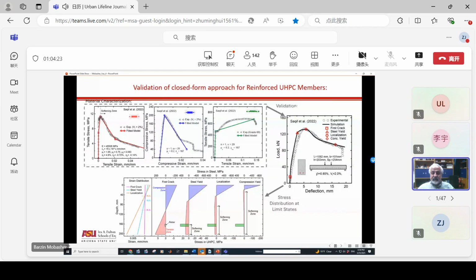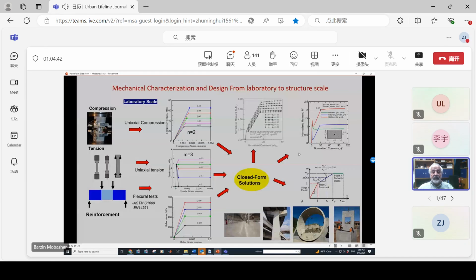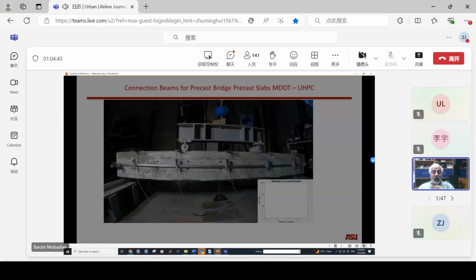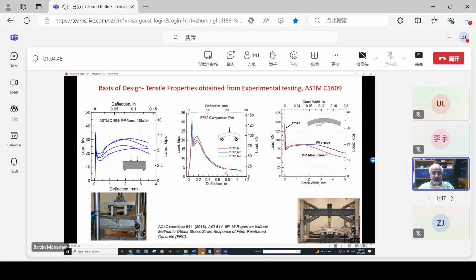When we look at the stress distribution across the section, for any strain along the length, I'm getting almost similar stress. So the variation that I have along here naturally dies out when I calculate the moment due to here. So that is the averaging process that would allow me to measure the response of the large scale specimens versus the small scale specimen. So this is a small scale specimen, large variation. This is a large scale specimen that has a much lower variation. And it's actually, this is what goes in service, not this one. So why am I penalizing this with this?